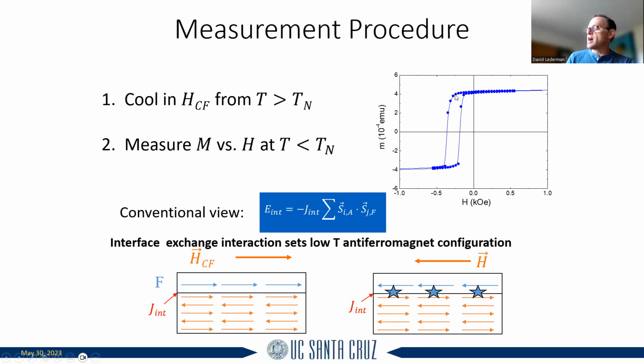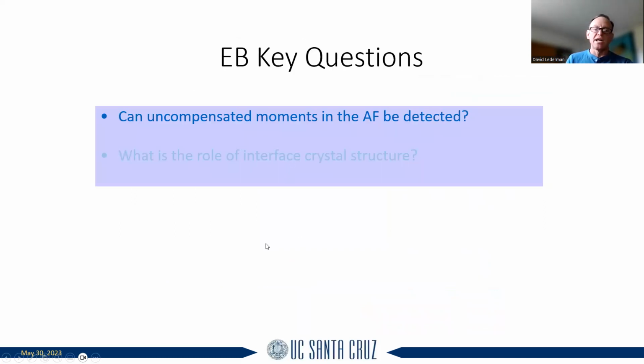This is some actual data from an iron fluoride antiferromagnet with, I believe in this case, iron on top, or it might have been cobalt. I don't remember this one, but you can see that you get a very nice clean exchange bias. And then the question is, okay, why is it that you have these uncompensated moments when you have a compensated surface? And so that's sort of what I want to address.